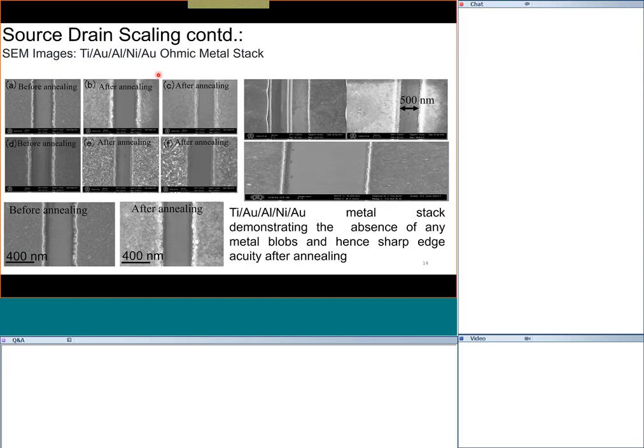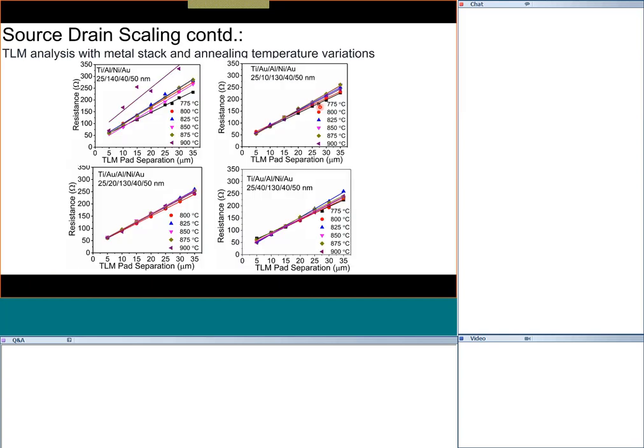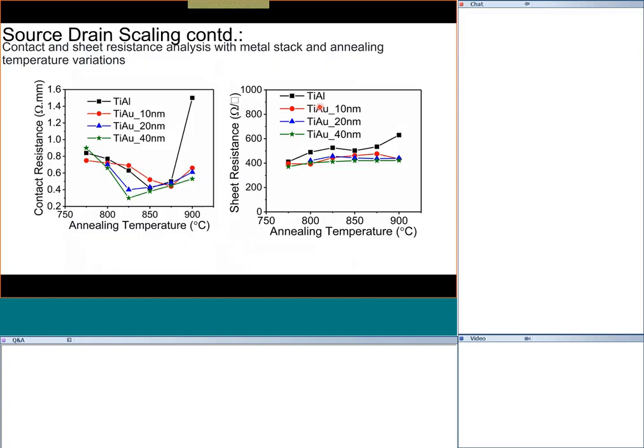What we did: by inserting a layer of gold between titanium and aluminum in the stack, you can see that after annealing the whiskers are mostly gone. This is a small piece of device and material engineering that gives a lot of benefit. Once the whiskers are gone, you can place the gate between source and drain without worrying much about shorting. A larger process window is also obtained — even if you change the annealing temperature, the contact sequence does not change much.